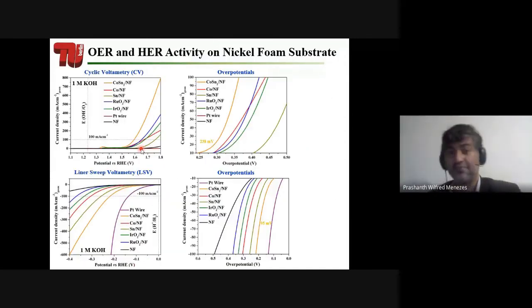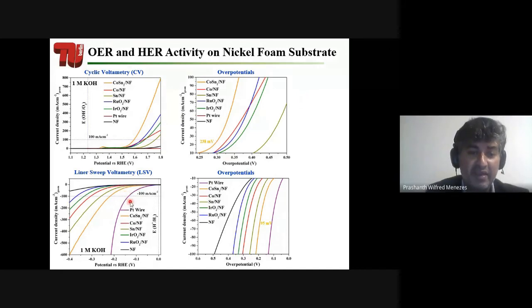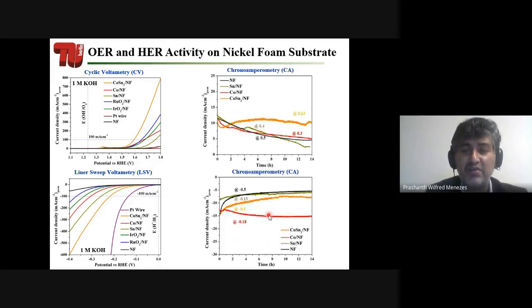Okay, this is the activity of our material. What you see here is that cobalt tin is much better for oxygen evolution reaction, also for hydrogen evolution reaction. But again, platinum is still the best for hydrogen evolution reaction. However, if you look at the overpotential, we are gaining a much lower overpotential, which is almost 238 millivolt for oxygen evolution reaction, and very low, almost 95 millivolt for hydrogen evolution reaction.